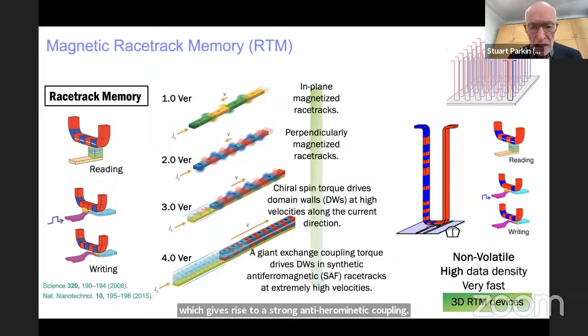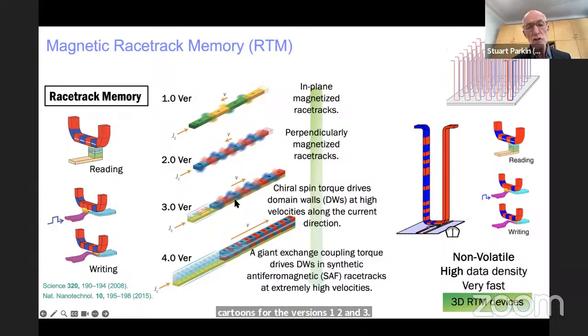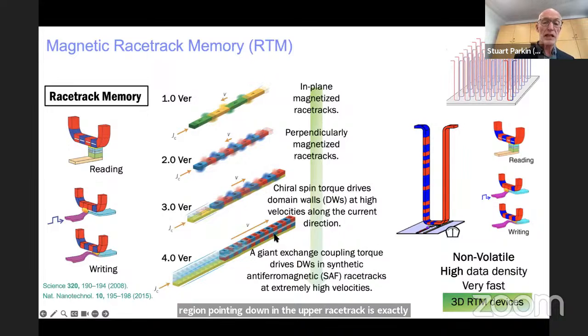Again, this is something that I showed a long time ago, 30 years ago, and I proposed using a synthetic antiferromagnet to eliminate the dipole fields, which I already showed you are so important, and which would otherwise give rise to interactions between the domain walls, as shown in these cartoons for versions 1, 2, and 3. They are so large, these fringing fields on the nanoscopic scale cause interactions between the walls within and between neighboring racetracks. However, in the synthetic antiferromagnetic racetrack, we eliminate the dipole fields because, as you can see in this cartoon, a red region pointing down in the upper racetrack is exactly on top of a blue region pointing up in the lower racetrack. So we can design the net magnetization everywhere to be 0, and there to be effectively no long-range dipole fields. Very important.